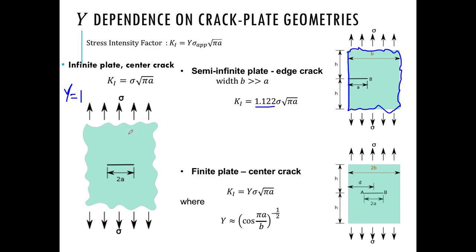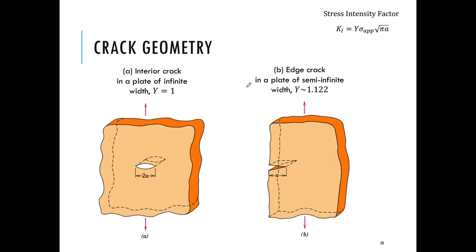For a finite plate with measurable dimensions containing a center crack, Y takes an expression in terms of the plate dimensions. Also note that the measure of crack length a differs depending on the geometry: for an infinite plate with a center crack, only half the total crack length (a) goes into the expression, whereas for an edge crack in a semi-infinite plate it is the total crack length. Be mindful of which crack length goes into the stress intensity factor expression.